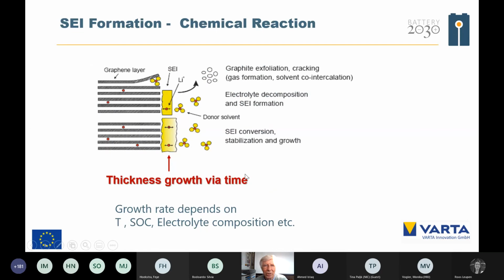So the good thing from one side is the SEI is avoiding the graphite exfoliation, the cracking of the graphite. So normally, without the SEI, the lithium ion is going into the layers between the graphene layers, solvated. So you could see that here. And that solvated lithium ion is much larger. And so the graphene layers will be exfoliated. And if you have the SEI, then that's very good. You have no more exfoliation, and the lithium ion is not going in the solvated state, so it's going only as the lithium ion in the graphite.